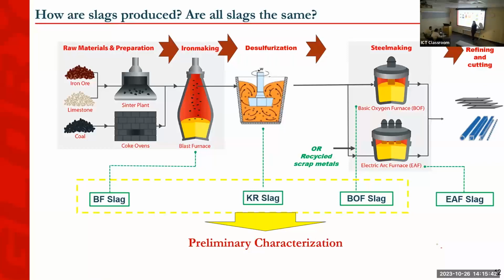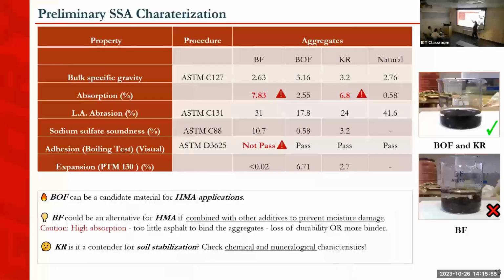So to do that, what we did, we selected those 3 slags here, which were the ones that were available in Brazil when I started to work with slags, and we did a preliminary characterization. Very simple characterization, common aggregate properties that state DOTs do. So we checked bulk specific gravity, absorption, Los Angeles abrasion, sodium sulfate soundness, adhesion, and the expansion of this slag. So what we noticed was that BOF, basic oxygen furnace slag, passed the requirements for aggregates to be used to produce asphalt concrete.